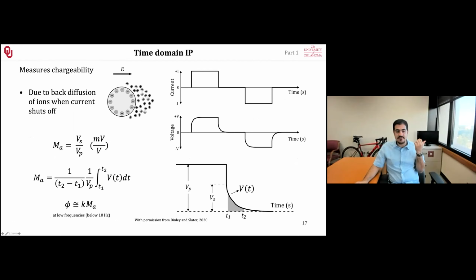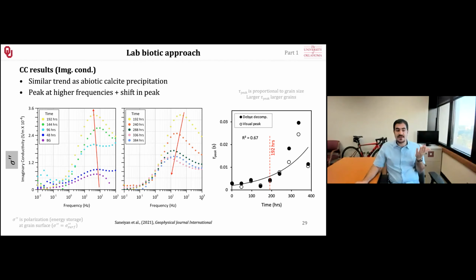Now, if we can actually measure this with the complex conductivity method as a multi-frequency method, we can convert frequency to time, right? Initially, it took them shorter times, or larger frequencies, basically smaller precipitates or powder, finer, right? And then as we kept injecting, they coagulated and produced larger crystals. So it took the ions more time to get redistributed. So we were actually able to show that the calcite crystals are increasing in size with this geoelectrical measurement that we were unable to show with the shear wave velocity, for instance.